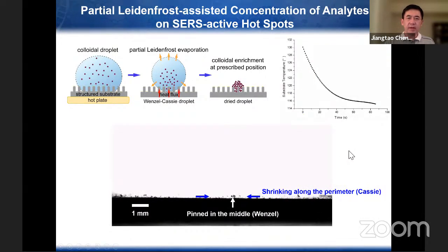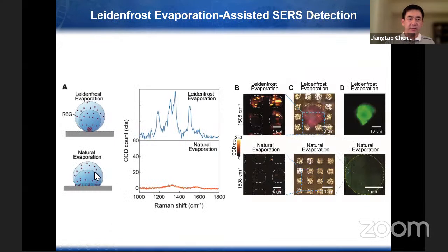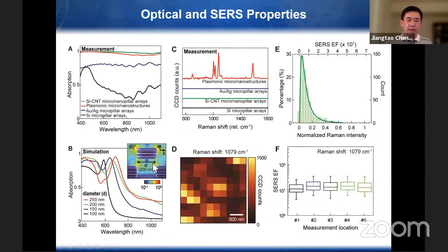Okay. So based on the partial Leidenfrost evaporation, we compared the natural evaporation SERS spectrum of the analyte. So that's relatively very weak signals. But with the Leidenfrost evaporation, we can see significantly distinct and apparent SERS signals. And we can also use the FDTD simulation. So those are the hotspots along the carbon nanotube nano antennas. So that's the vertically distributed hotspots. Okay, and also the silicon carbon nanotube hierarchical plasmonic structures can absorb almost 100% of the incident light, and the SERS enhancement factors can reach above 10 to the power of 7.